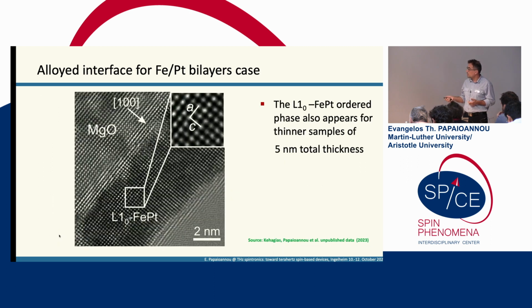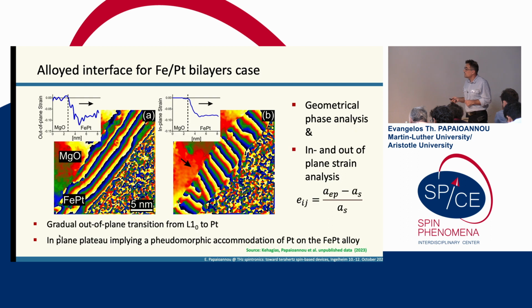along our sample. So we are looking at here the strain that is induced along this is the growth direction, and along the in plane, so perpendicular to the growth direction, and you see a very strange behavior. So here, in principle, out of plane, you can see that you start with MgO, our reference. This is the strain that is induced from this relation, where we have the strain of the layer above the substrate, and here's the substrate.